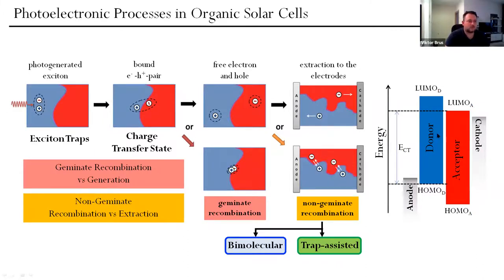so-called donor and acceptor. So why donor? Because donor provides electron and acceptor accepts electron. So why does it happen? It happens at the interface because we have band discontinuity, LUMO-LUMO and HOMO-HOMO discontinuity at the interface. So because of this discontinuity, the gap here should be enough to overcome the exciton interaction energy and split the exciton into free electrons and holes. So the free hole remains in the donor and energetically it is favorable that the electron will be accepted by this acceptor material.